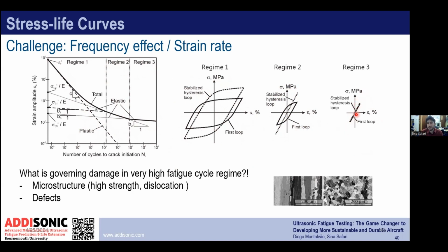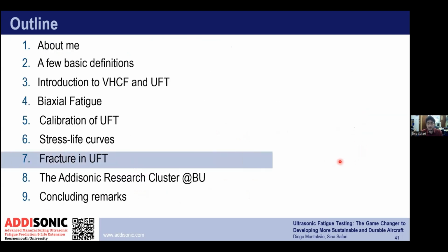So the question of where the damage is coming from actually comes from the microstructure. What is actually governing the damage in the very high cycle regime, I would like to answer, is the microstructure. If there is a very small microstructure defect, or after many cycles, if there is microplasticity in some region of the structure, it starts to develop. So in the very high cycle fatigue regime, the microstructure is very important, and this is one of the challenges that should be addressed.